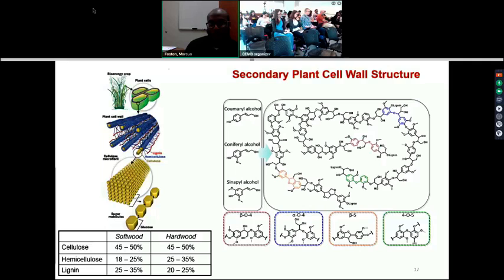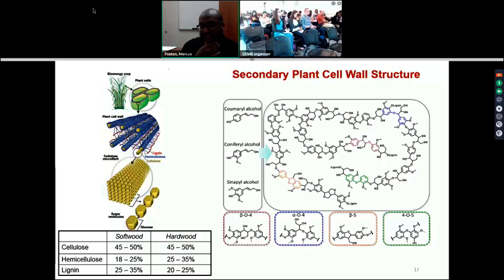Lignification is a very common strategy in both hardwoods, softwoods, and grasses. Secondary cell wall lignification also serves purposes of structural rigidity and water transport — cells designed for water transport need a proper balance of hydrophobic and hydrophilic surface properties to take advantage of capillary forces for wicking water up, sometimes hundreds of feet through a plant. Lignification adds tensile strength somewhere between 25 to 75 megapascals and adds Young's modulus somewhere between 2.5 and 3.7 gigapascals.